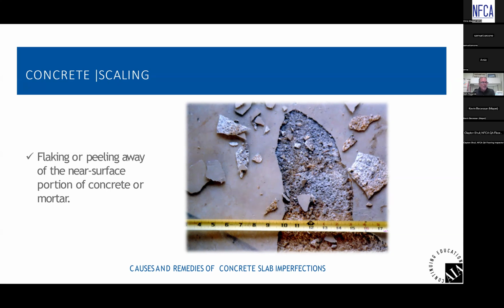Because what happens is if you steel trowel air entrained concrete, you'll create a layer of air bubbles directly beneath the surface. And when everything is cured out, you've got a layer of air voids directly below the surface. Any type of force will break that weak layer of air voids, and the whole surface scales off, like you see in the picture here.